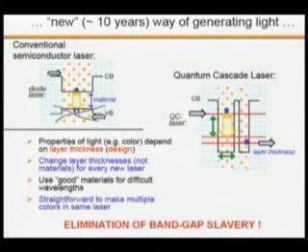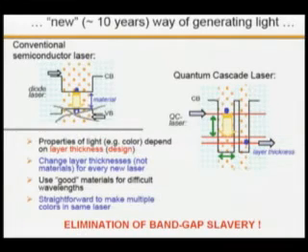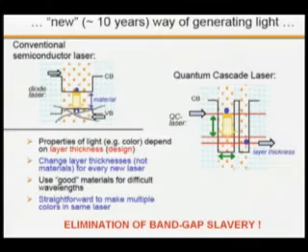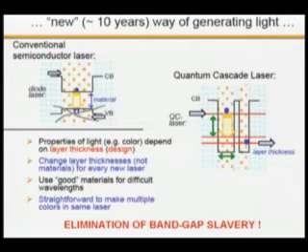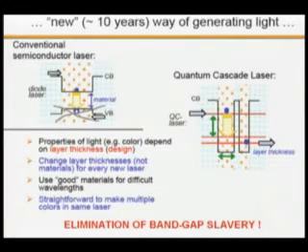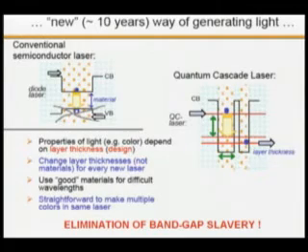In a quantum cascade laser we essentially eliminate so-called bandgap slavery. The wavelength is no longer determined by the bandgap of the material, because we lase between discrete quantum states of quantum wells that we can design, so the wavelength spans a very wide range. The frequency of the photon is limited by the depth of these quantum wells. By staying in the same material system, we can create lasers with a tremendous range of wavelengths, covering potentially the entire mid- to far-infrared by simply tailoring layer thicknesses. This is an example of quantum design — bottom-up, we design everything quantum mechanically.